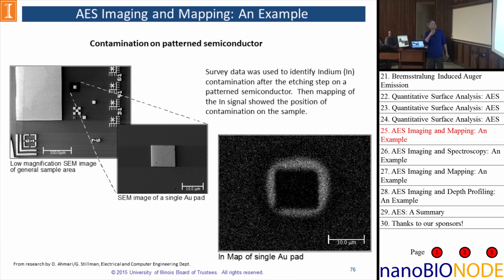So we located a little pad right here, increased the magnification, then switched over into Auger mode, collected an indium map, and we see that the etch process did not fully remove indium from the edges of the pad. And so that would be an example where these people would have to modify their etch process to correct that.